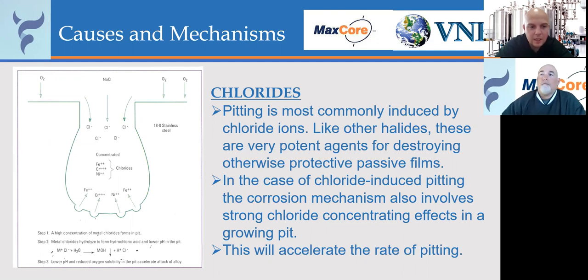Is there like a delay, Ken, between when this starts and when we start to visually see it? I feel like sometimes people have a problem long before it's visually apparent. A lot of times you can, yeah. Many times you can look at the surface and you can actually see what looks like an orange peel to the surface itself. If you have a nice mechanically polished surface, you can actually see something that looks almost like an orange peel or a discontinuity in color, more of a gray type color. You can take a bright white light, and you can shine it on the side of it kind of at an angle, and you can maybe see like little stars on the surface of a tank. That's an indication of micro pitting starting to take place.